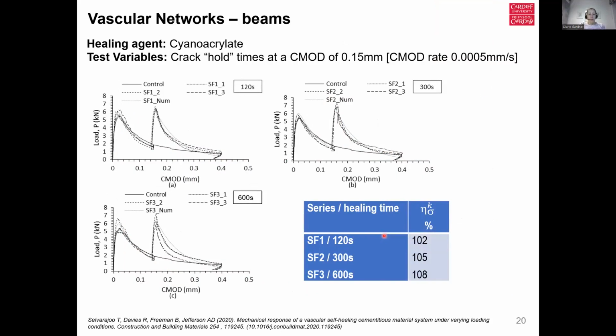Taking that work on further, then we looked at cyanoacrylate, and we looked at a series of tests in which we could actually hold the crack open for certain durations of time at a crack mouth opening displacement of 0.15 millimeters. And what this really was aiming to do is to demonstrate whether we could eventually get to simultaneous damage and healing with our cyanoacrylates. And the work has also confirmed the benefits of pressurizing the healing agent and determine the optimum pressure range for a certain type of healing agent.